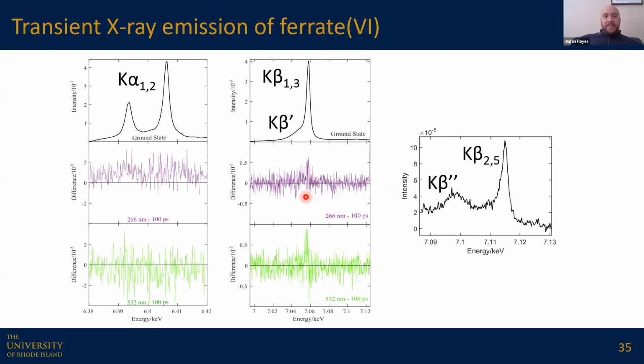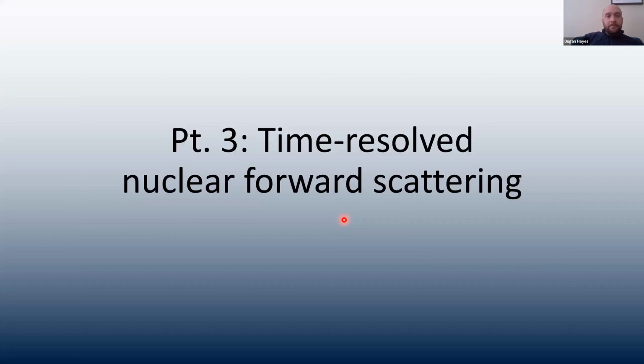In the K beta, however, we see evidence for a slight increase in the K beta mainline, and perhaps a bit of a bleaching on the blue side, which I don't really have a good explanation for. We need to try to see what we can do in terms of binning this data to improve what we can see here. And then we also have the valence to core data, which was very exciting for us as well. So this is the status of that. I would like to revisit this in the future to try to improve what we can see in the K beta and see if there is a difference between UV and visible excitation, and the branching of those two different pathways that we might see at later delay times only following UV excitation.